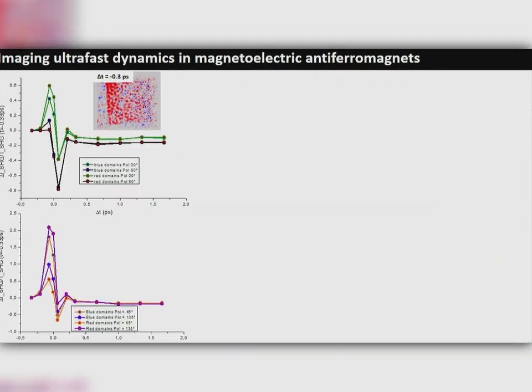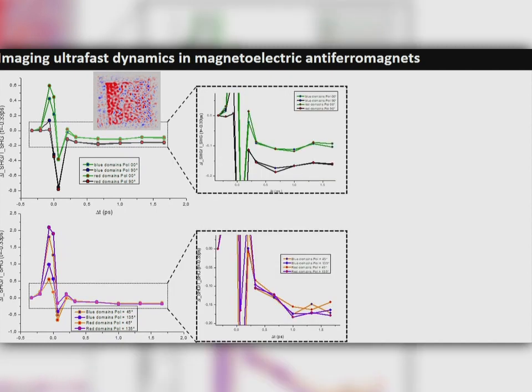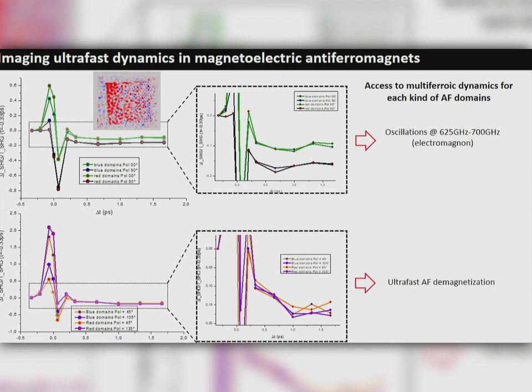To do this, we go to each kind of domain and trace the time evolution of the second harmonic signal. The nice thing is that by doing this, we can really identify a family of antiferromagnetic domains and track the time evolution of the dynamics. Here we can see two kinds of things. The first is what's happening after the excitation, and we can note two things. First, the onset of an oscillation at about 600 to 700 gigahertz, which we can think of as the electromagnon in bismuth ferrite. And at 45 and 135 degrees, where the magnetism is the most active in our signal, we see a decay of about 1 picosecond, which is the signature of ultrafast demagnetization in this process.